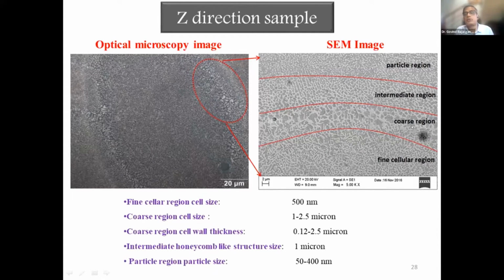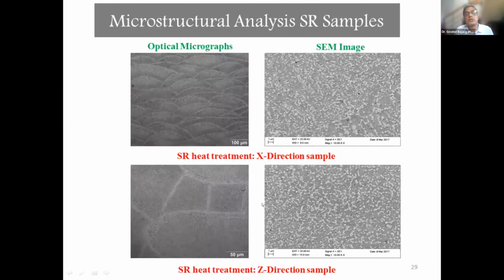The intermediate and coarse zone is a partially melted zone, because eutectic melts at slightly lower temperature. So that is where we see a partial melting. And the particle zone, where the cellular wall has converted into fine particles, is heat affected zone away from the partially melted zone. If we stress relieve such a structure, we get coarse particles, but coarsening is higher in the HAZ zone.